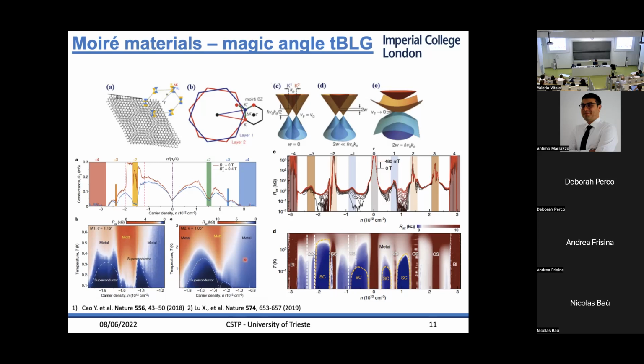And this was the first example of this system. You know, graphene doesn't have all of that; it's not a superconductor, it's a semi-metal, right? And on the right, people managed to have a cleaner device where they could show that basically these superconducting states were at specific filling or fractional filling. And between these, you have these charged correlated insulating states.